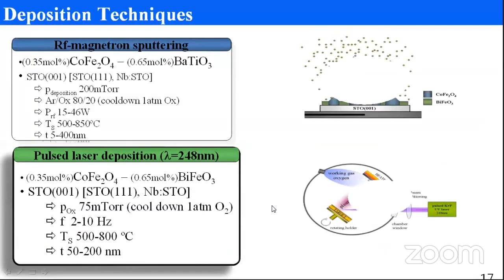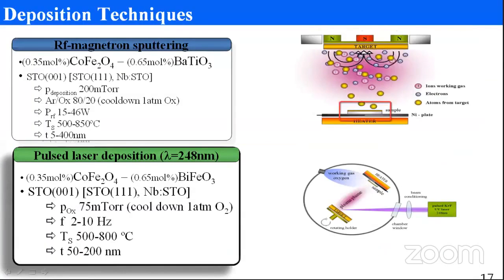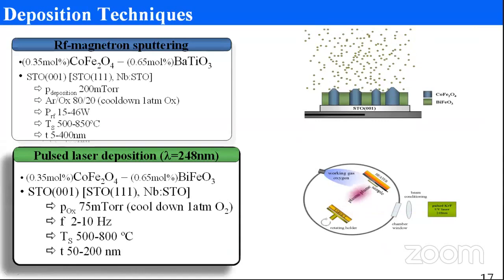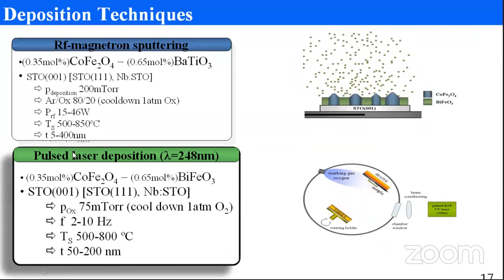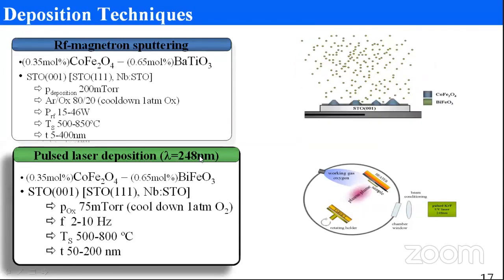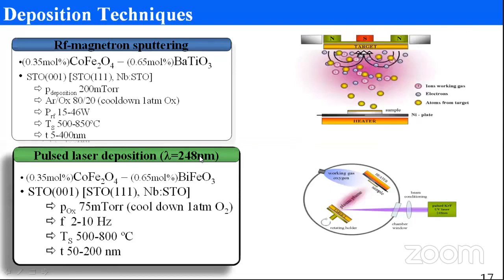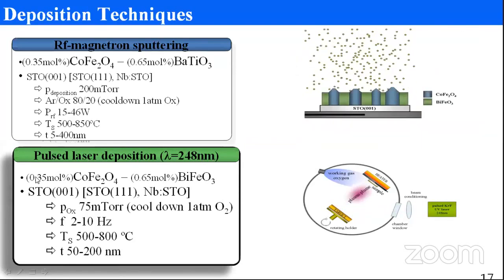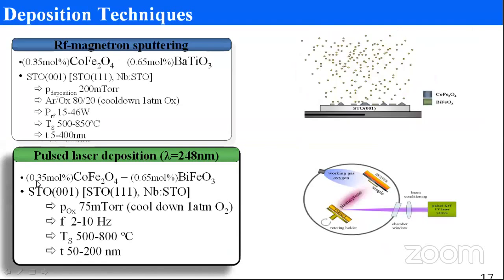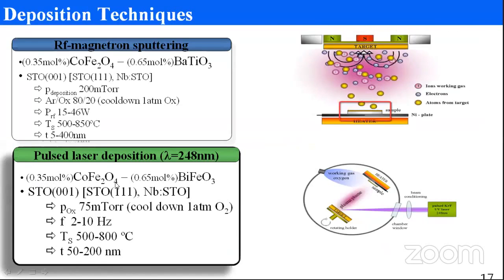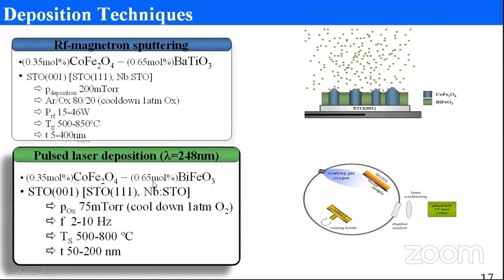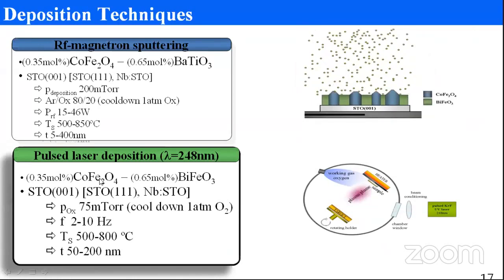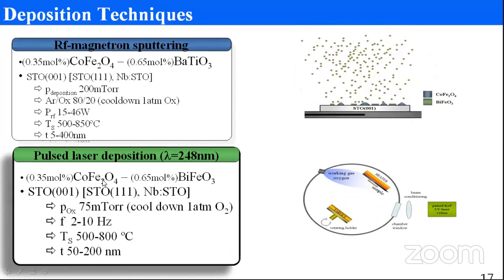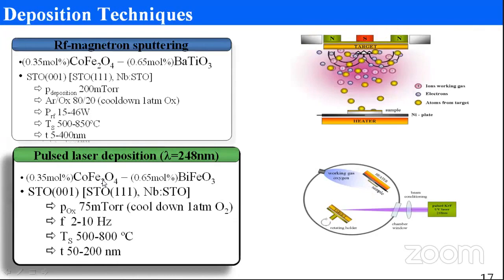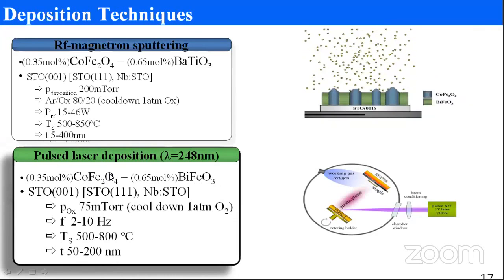Okay, so most of the films which I'm going to present here were prepared by pulsed laser deposition, and I'm going to take only one composition, 0.35 cobalt ferrite, 0.65 bismuth ferrite. This is one of the compositions which showed very good properties. So we stick to this composition.